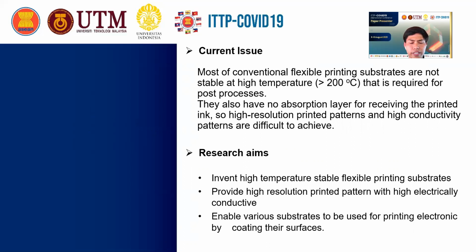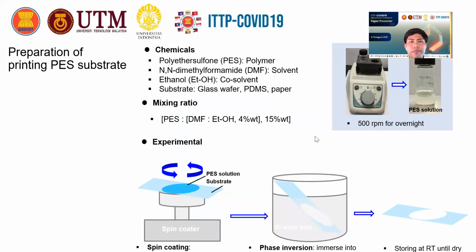Those printing substrates are not high temperature stable. So we try to invent a high temperature stable printing substrate, and we want to make a printing substrate that can provide a high resolution printed pattern. So very small, tiny electronics can be made, and we want not only to make the substrate itself, but also to coat it on another printing substrate to make it printable and maintain high resolution and high electrical conductivity. So we came up with a method.